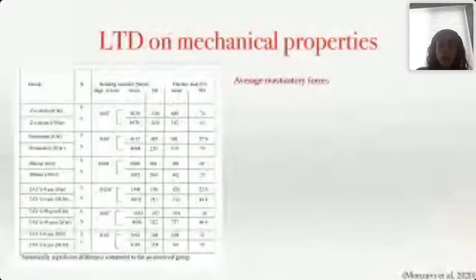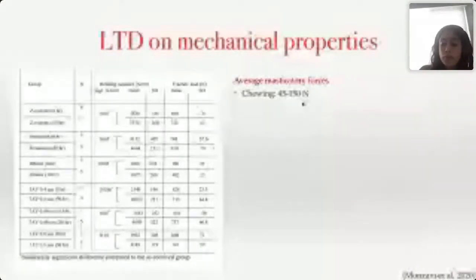This is the Stroman, Z-bone, and TAP group. The fracture load is shown here, how much Newton load was applied until the implant fractured. During chewing, we use about 45 to 150 Newton, and you can see all these fracture loads are way above the chewing force. Even the group with the lowest fracture load was still way above the chewing force.